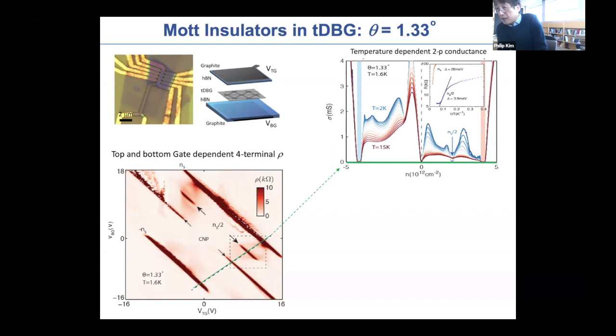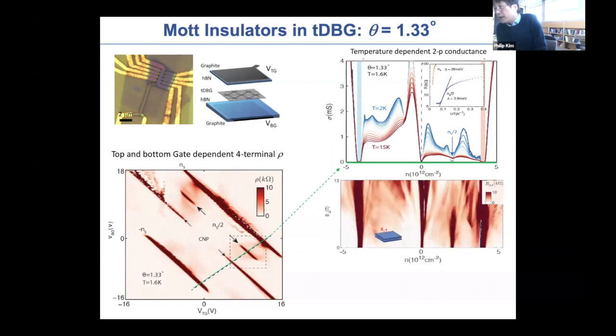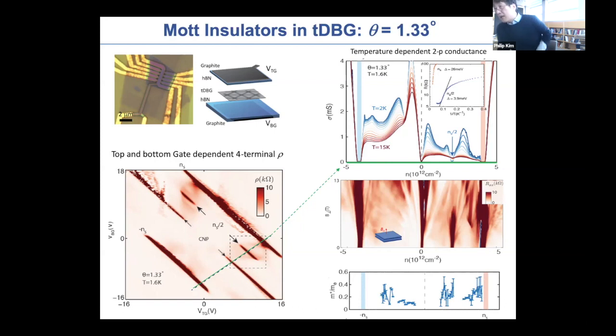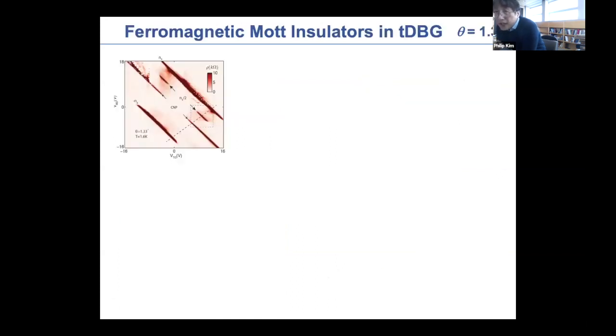So a sizable gap appears, and you can apply the magnetic field and get the band mass around there. And the band mass is much more enhanced than the single particle band mass estimated from the band structures near this half filling gap, indicating this half filling gap is indeed likely a correlated gap, one that you can get similarly in the magic angle twisted bilayer, except that here, in a sense, the magic angle is realized by using the displacement field as the control parameter. And one can actually study the nature of the insulating gap by applying an in-plane magnetic field.